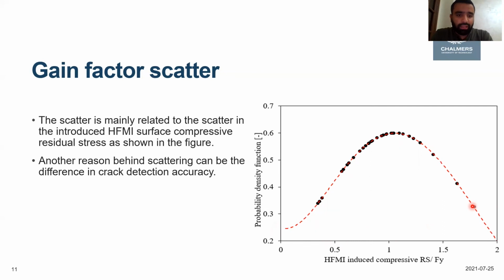Another factor is the difference in crack detection accuracy. In some papers, the crack size was quantified very precisely because the crack was created artificially, so we have pre-knowledge of how large the crack is. In other papers, we use a crack detection method like ultrasonic testing. In other papers, we use less accurate detection methods such as dye penetrant and so on. That will of course be reflected in the gain factor.